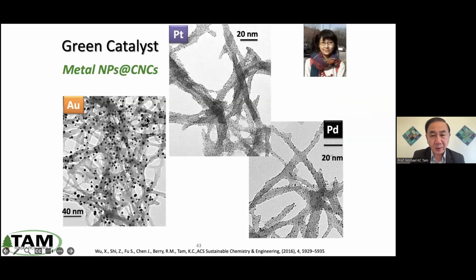We can nucleate gold or platinum or palladium, and we see that the nanoparticles that we're able to put on the surface are very, very small. They are less than 5 nanometers, which means that we can substantially increase the surface area and the processability of this nanoparticle to make sensors, to make catalysts and different types of application.